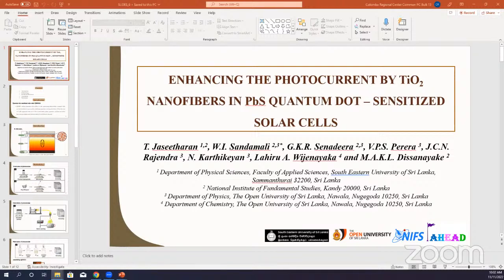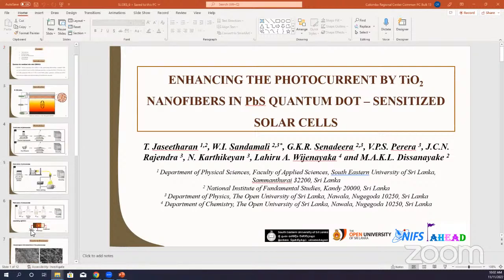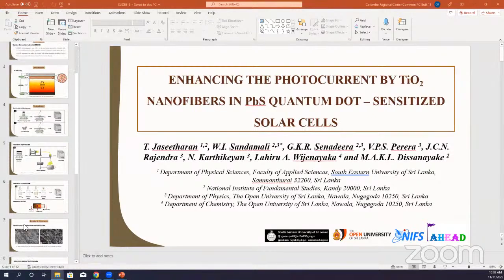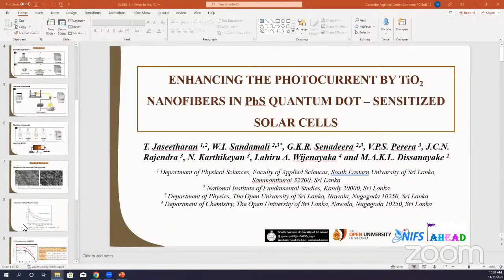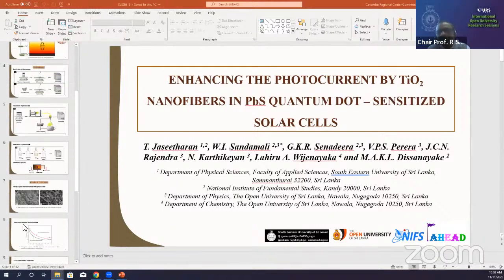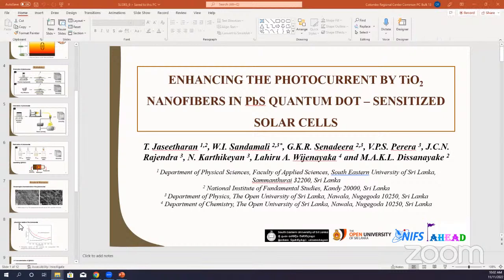Then you believe that nanoparticle formation in the fabrication is completely working? Yeah, it works because I confirmed it. I think here we didn't report the TEM image of the PbS quantum dots, but we have that image. Because I controlled the size of the quantum dots, and I got the TEM image, as the number of SILAR cycles increases, the size of the quantum dots will increase. But big size may reduce the efficiency. Quantum dots of size around 10 to 20 nanometers perform well.